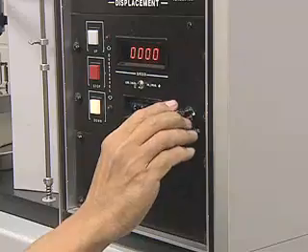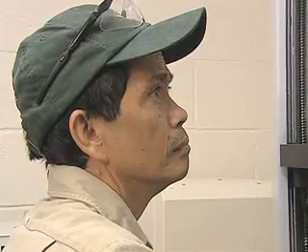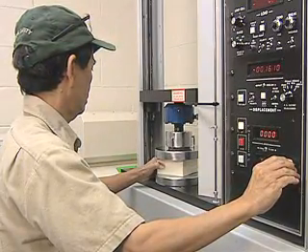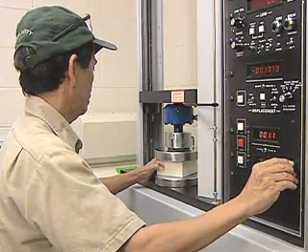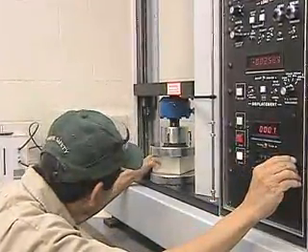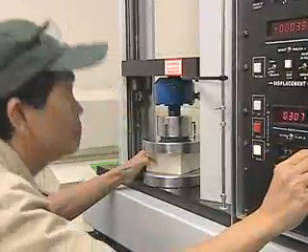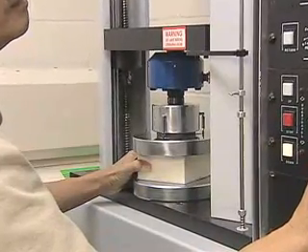Hunter is, to a great extent, defined by its quality procedures and maintains a fully equipped QC lab staffed with process engineers. The compressive strength testing underway here is fundamental to achieving high-quality polyiso panels, as are the side compression, density, and facer peel tests routinely performed according to industry performance standards. Hunter's processes are continually audited by Factory Mutual, Underwriters Laboratories, and the PIMA Quality Mark program.